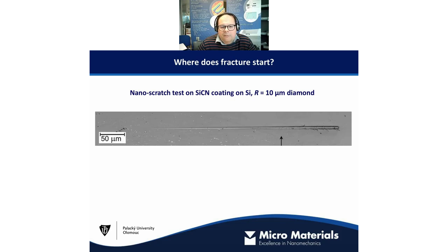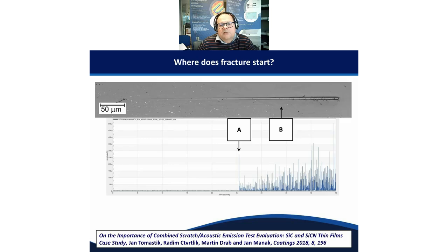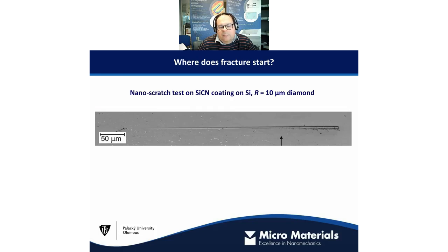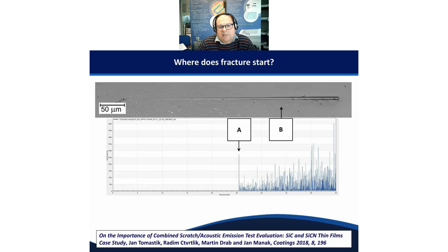So we can combine the system with a high resolution acoustic emission sensor. Point B corresponds with this point here. This is where we could see a failure happening and we could see something on our scratch test data. But our acoustic emission sensor tells us that a failure is occurring a lot earlier than that. Here we've got crack events which are so small that we're unable to detect them through friction change or through a depth change. But through an acoustic emission sensor, we can pick things up much, much earlier. So you've got a range of instrumented signals that you can use in conjunction with one another to get a full picture of what happens during your scratch test.